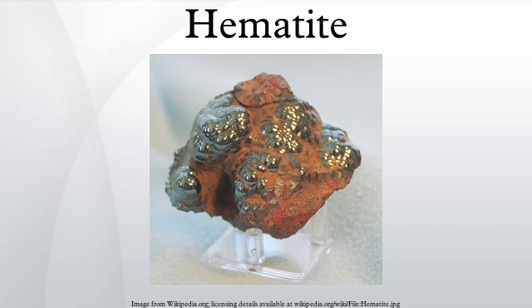The magnetic properties of bulk hematite differ from their nanoscale counterparts. For example, the Morin transition temperature of hematite decreases with a decrease in the particle size. The suppression of this transition has also been observed in some hematite nanoparticles, and the presence of impurities, water molecules and defects in the crystals were attributed to the absence of a Morin transition. Hematite is part of a complex solid solution oxide-hydroxide system having various contents of water, hydroxyl groups and vacancy substitutions that affect the mineral's magnetic and crystal chemical properties. Two other end members are referred to as protohematite and hydrohematite.